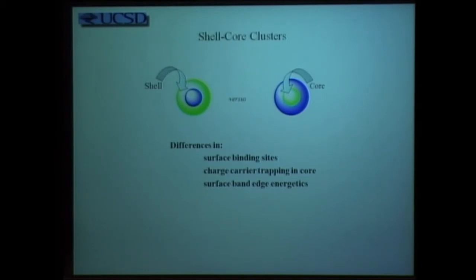You'll see differences in surface binding because on one of the particles you have green on the outside and the other particle you have blue on the outside. You'll have charge carrier trapping in the core, just as we did with platinum in the preceding series. And you'll have surface band edge considerations if the active material is on the outside. So being able to think about shell core clusters is one way of thinking about absorbing light and getting it to the right place so that chemical reactivity can take place. Here's another example.